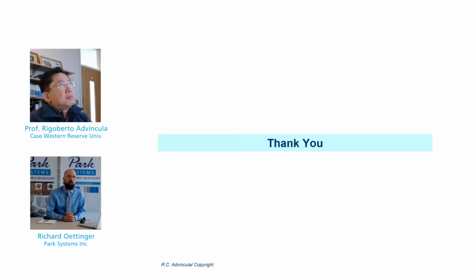It's not possible to measure or quantify specific islands or domains with an AFM tip unless you have a very good correspondence with the surface energy between the tip and the morphology. However, what we will generally do on the patterned surface or simply the grafted surface is to do dynamic contact angle measurements. Although that is more general, yet it is revealing in terms of some of the surface energy and morphology of the surfaces. But it's possible, of course, to use atomic force microscopy. Again, you have a very good correspondence between the tip surface energy and the substrate, as well as a good calibration method.